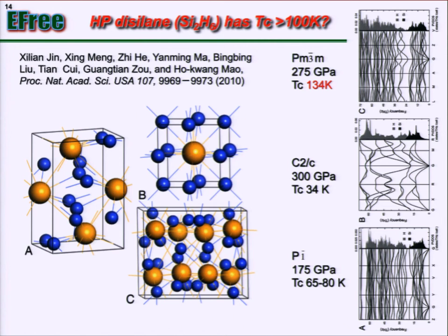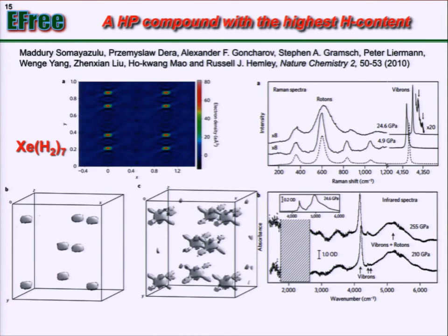this Si2H6, predicted to be a high TC, high temperature superconductor at 134 Kelvin. This has not been synthesized. This was only calculation. And this one was synthesized. This one has more hydrogen than any other known compound. We made a xenon hydrogen compound, but the relation is still a van der Waals compound. So even when compressed to 200 GPa, this did not become metallic. So again, it didn't quite work out as we hoped.